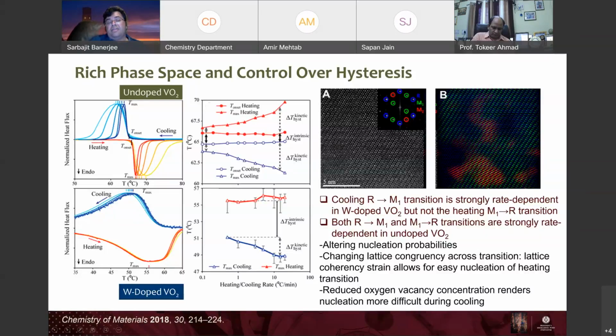And tungsten doping happens to reduce the defect density, and so it makes the transition very difficult because there's no oxygen or a lower amount of oxygen vacancies. And so this results in the transition being shifted down, and we end up getting a lot of hysteresis.